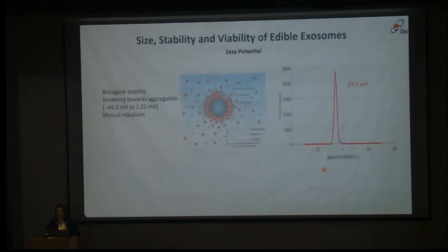Not only this, like every cell has a charge, in a similar way exosomes are not inert. They also carry a charge on top of it. So the more negative charge, from minus 50 millivolts to 0, it shows that they have a tendency of not aggregating with each other. They are more stable, and they are biologically active. They mutually repel. So this zeta potential actually tells us whether it is inert or more stable and biologically active. So we get the result of their activity.